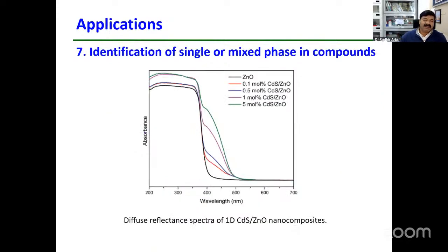Another one is that using UV-visible spectroscopy in DRS mode, we can identify whether the compound is single phase or multi-phase. See here what we did, we prepared zinc oxide and cadmium sulfide. You know that cadmium sulfide, visible light active, shows absorbance at 530 nanometer for bulk material, and ZnO shows absorbance at 380 nanometer. As we loaded cadmium sulfide on zinc oxide, varied from 0.1 to 5 moles.